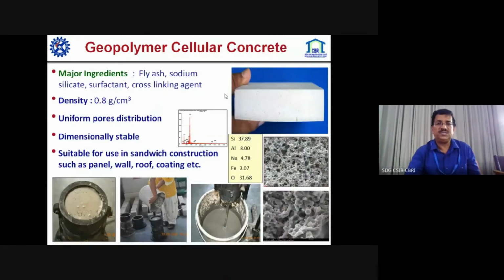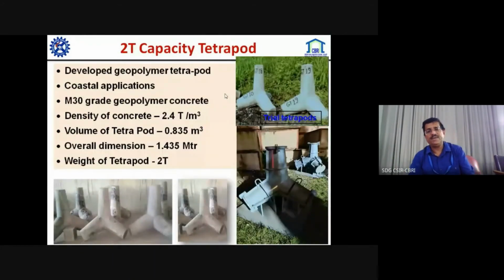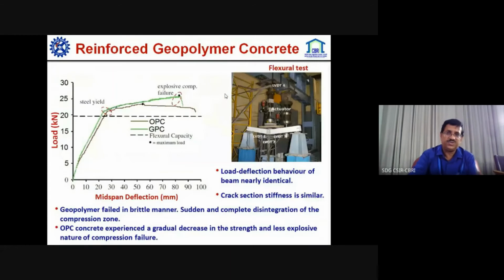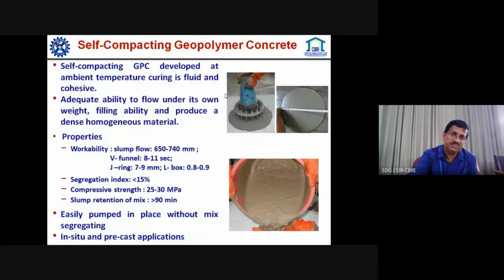These are the areas that we have worked on: cellular lightweight material with fly ash, because in cellular material we previously used cement. If you look at the AC block, aerated autoclaved and other things, we have done it with the geopolymeric material. We have made tetrapods, which I have told you are very good in the marine environment, as an energy breaker, so it is being utilized. Also, structural element studies have been carried out and found similar results.